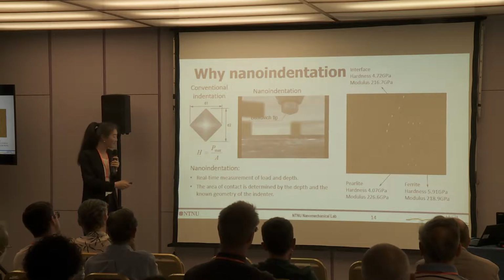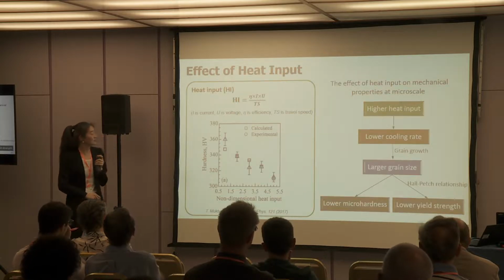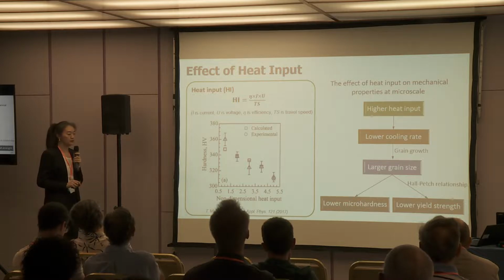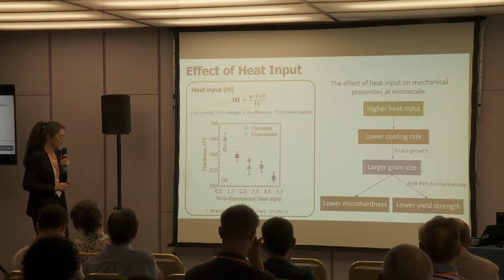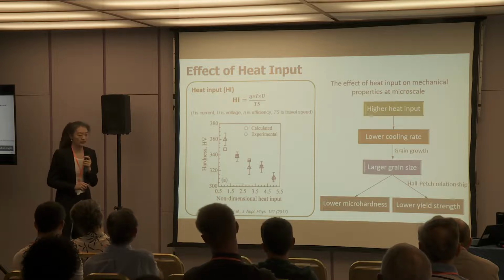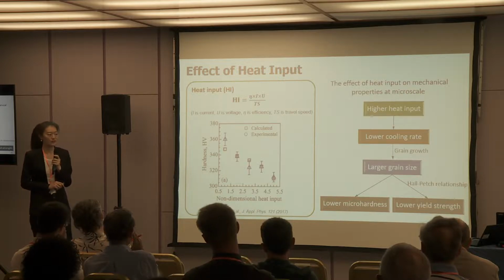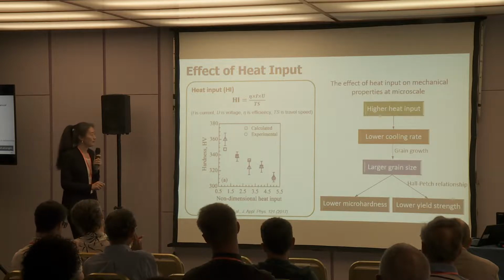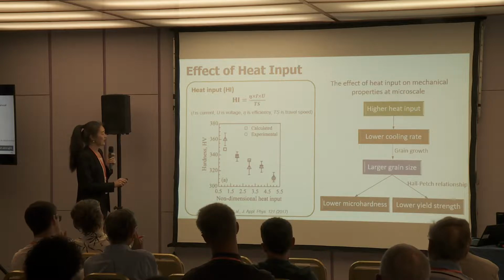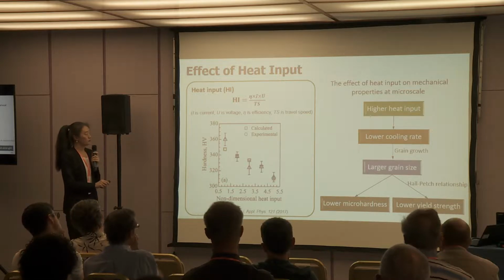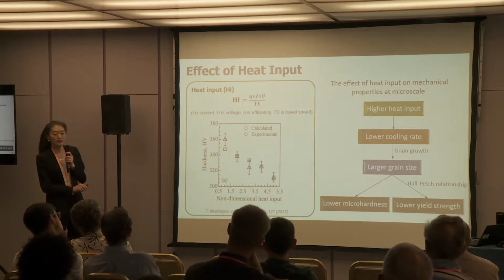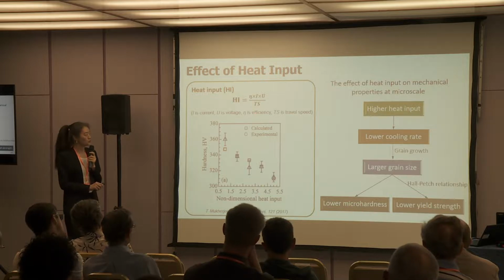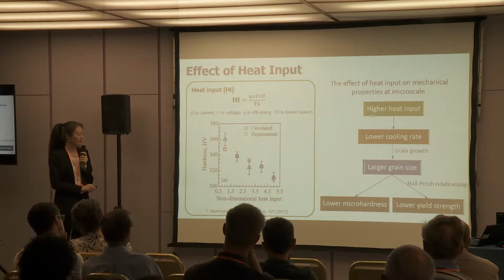Let's see the first example, how the heat input will influence the mechanical properties. Heat input is one of the most influential parameters during AM. And it's calculated as here, proportional to the current and the voltage, and inversely proportional to the travel speed.